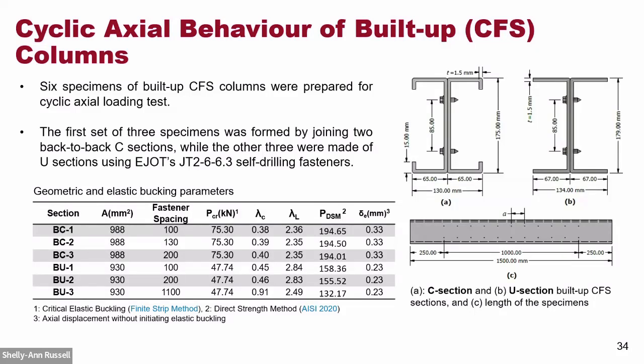Local buckling happens after a certain length continuously. The local buckling wavelength was 130 mm for, for example, this C section. So we chose the fastener spacing below this value and also a bit more, like 200, to see how it works. The critical local buckling of this section was calculated based on the finite strip method. There's a software called CUFSM, an open source software. So we can analyze these sections and find out the critical elastic buckling. And we estimated the compressive strength of this section using the direct strength method based on the American Iron and Steel Institute.